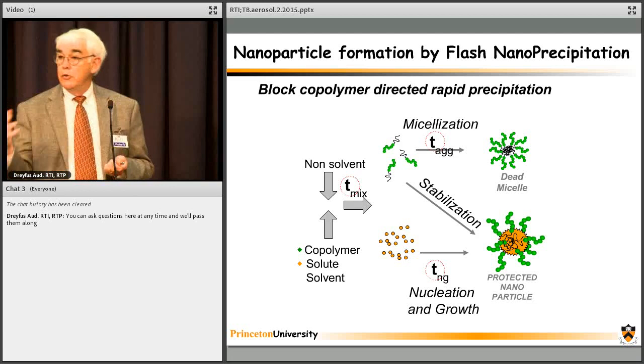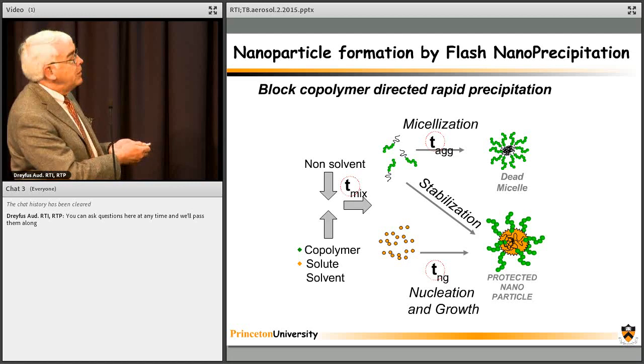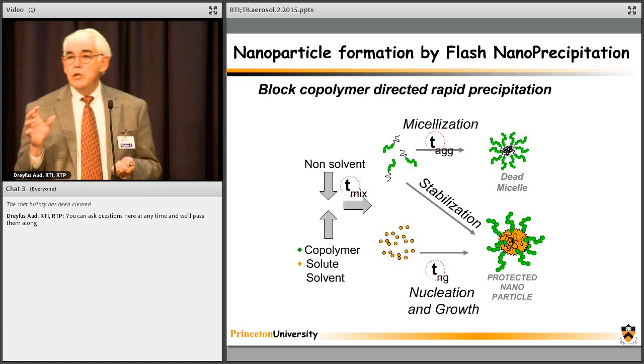And the small block copolymer. So it has a hydrophobic block, has a hydrophilic block. So that comes in on one stream, and then we're going to use these confined impinging jet mixers, which I'll describe, and the non-solvent is just water.